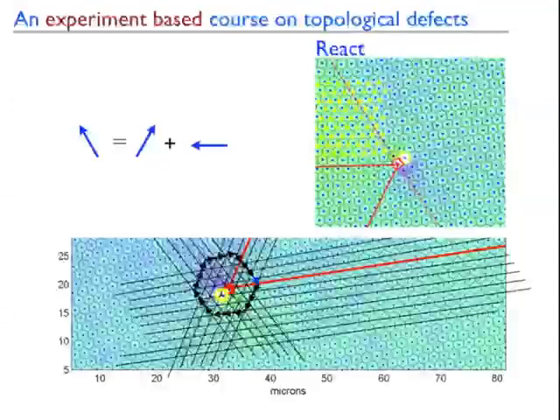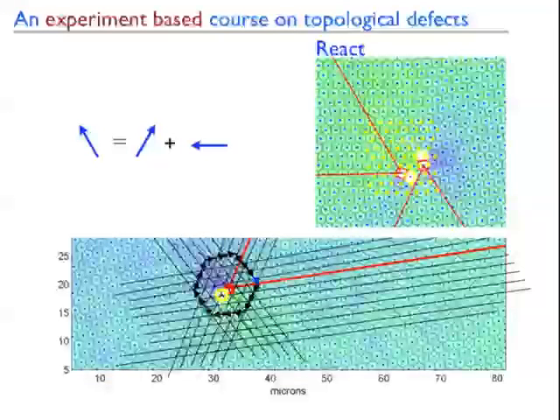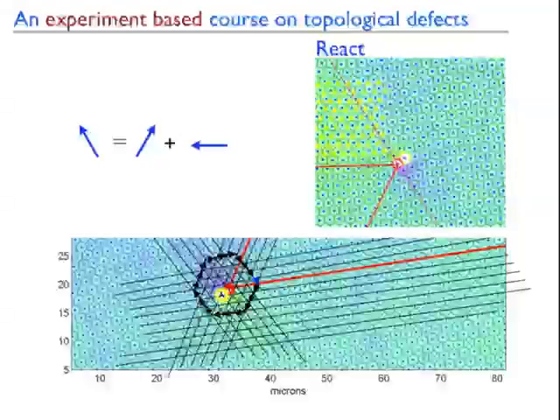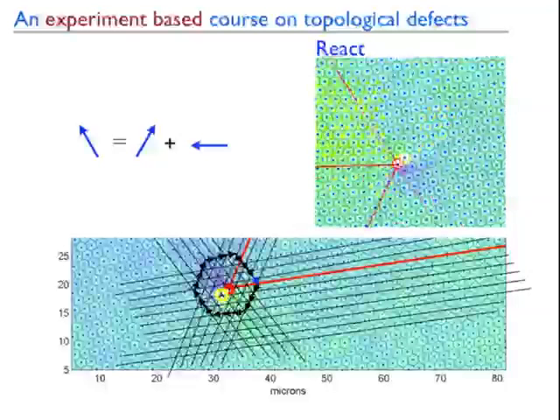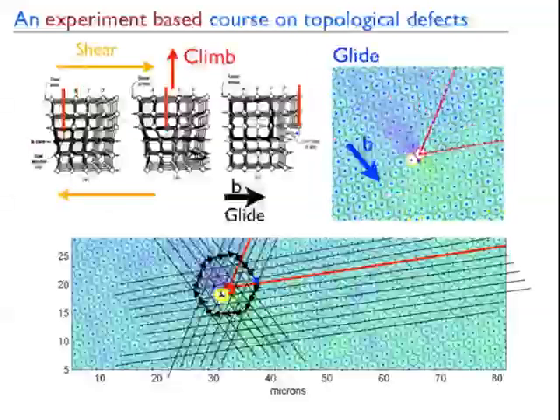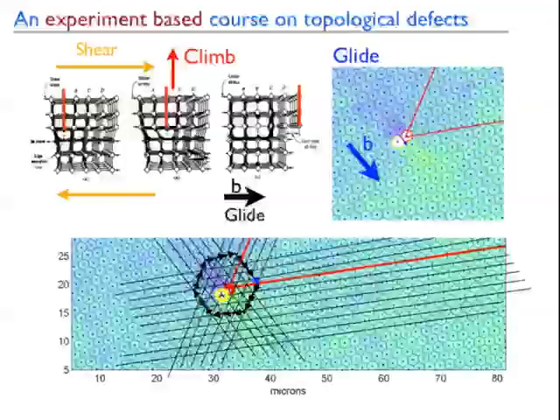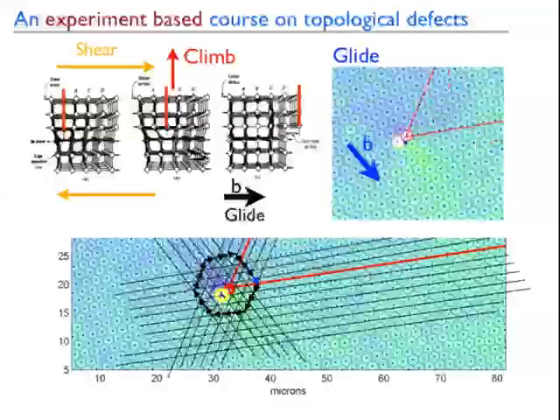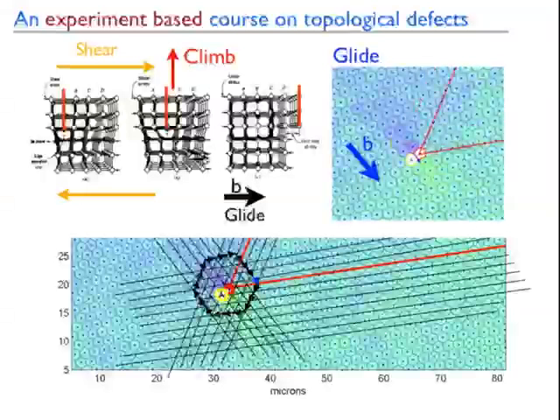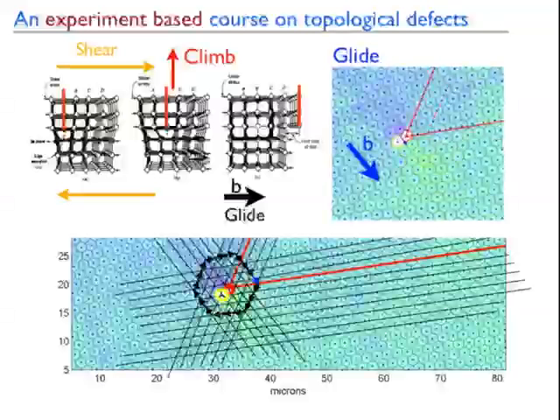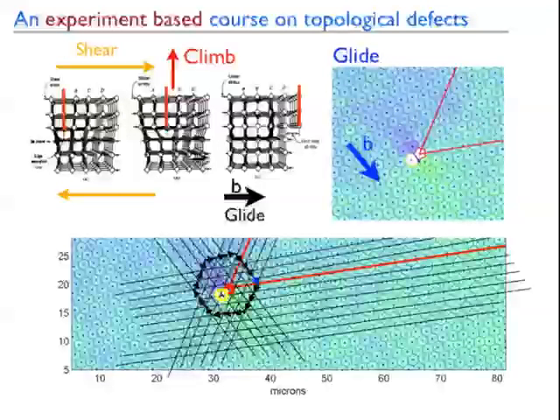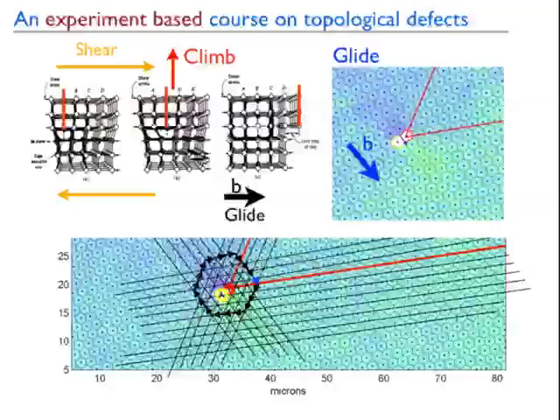They also, in a hexagonal lattice, react. That is, this Burgers vector is equal to this one plus this one. So I can take one dislocation there, and moving a set of optical traps over them, I can fission it into 2 dislocations, which move away. One of the things I should have said back over here is this motion, where the dislocation moves just by reassociating this with this and moving over. This is called glide, and that's what dislocations can do easily. Moving up like this is called climb, and that's next to impossible because it means I have to take a whole sheet of particles and move them essentially out of the crystal, right?